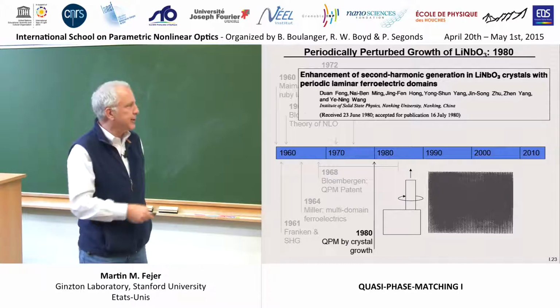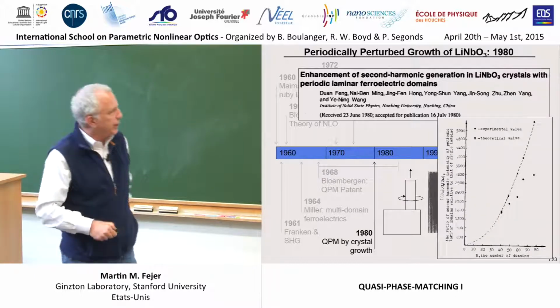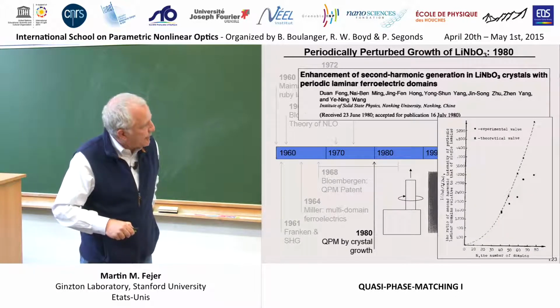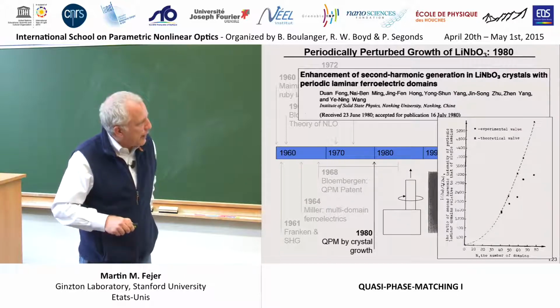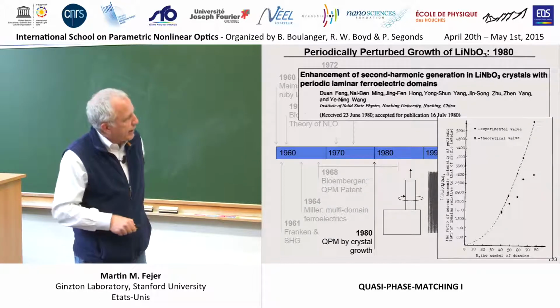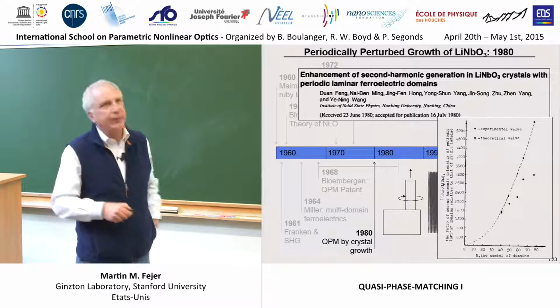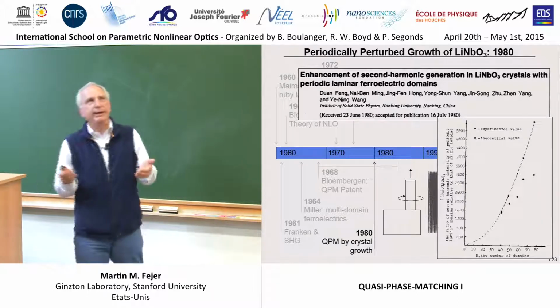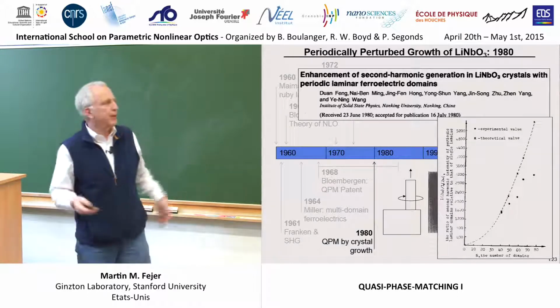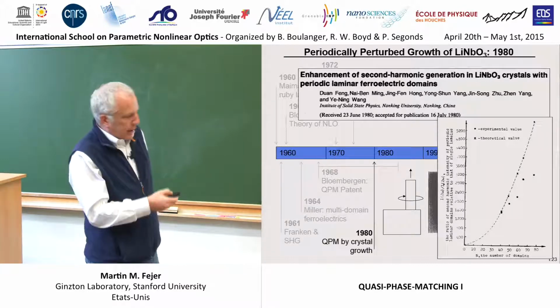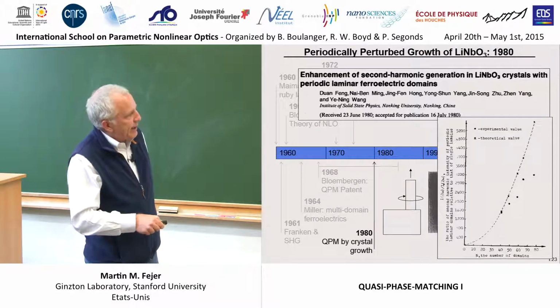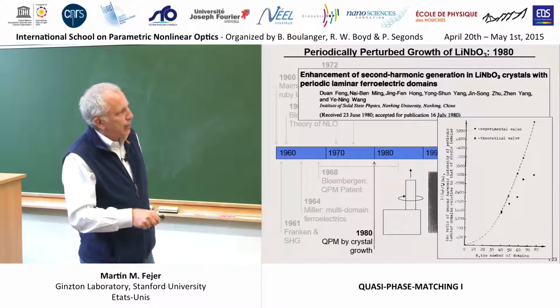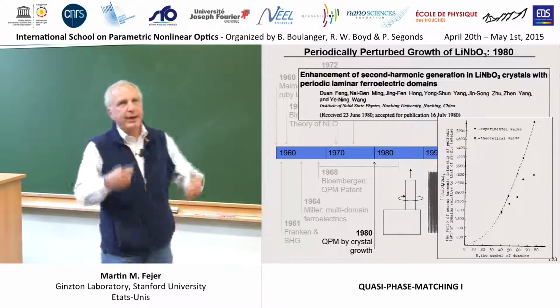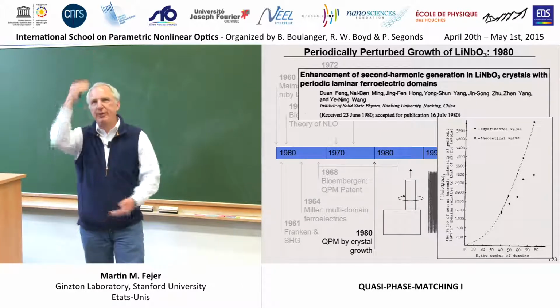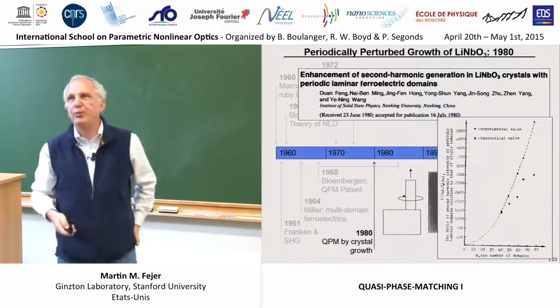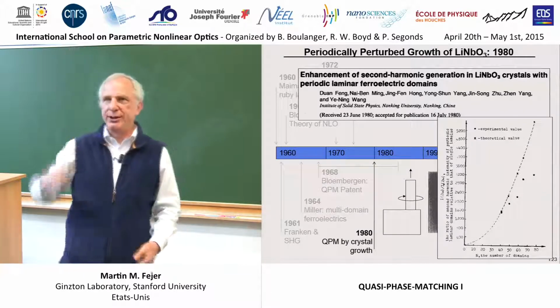control to micron accuracy. And in fact, if you look at their result, for the efficiency as a function of the number of domains, the thickness of their sample, they saw that up to maybe 20 or 30 of those, which is probably, I don't know, 100, 150 microns of material, it worked okay, but then it kind of flattened out and didn't work much better and fell below the theoretical line, and that's just the disorder that came from the fluctuations in the crystal growth, spoiling the long-range periodicity of this grating.